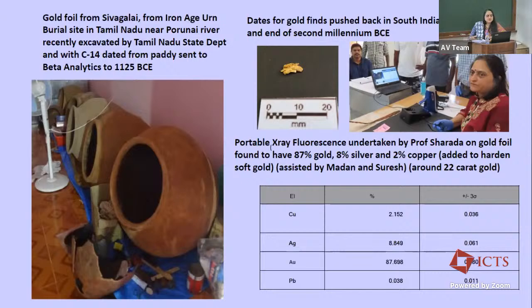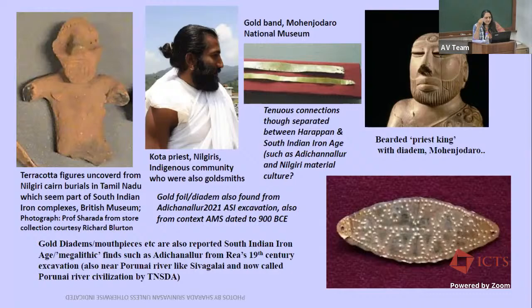And the advantage with gold is that it's not corroded, so you can get a very good result. Because if it is a corroded surface, then it's more complicated with XRF analysis. And you can see here that this had about 87% gold, which is actually the composition of 22-carat gold, and 8% silver and a little bit of copper. And the addition, of course, of copper to gold would have been also to harden the gold. And this is also in the shape of some kind of broken up gold foil.